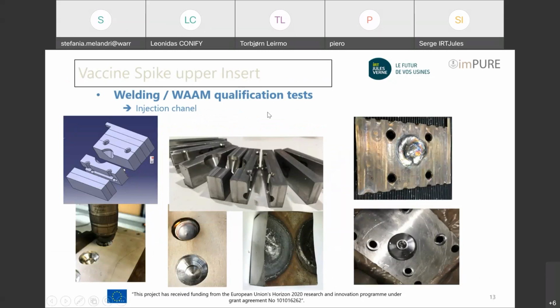So we had a specific qualification for the injection housing, because you see the housing was between 3 slices. And when it was assembled by TIG, we set here a first deposition by MAG process, and we refilled the hole just to make sure that we will have no leakage or no coolant feed during the injection.